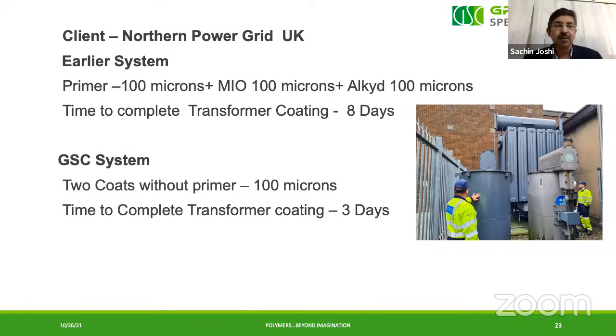And what are the systems? Earlier system: 100 microns primer, 100 microns MIO, and 100 microns alkyd. Time to complete transformer coating is 8 days. So 8 days your revenue is stopped. When you change to this, only 2 coats, 100 microns, and within 3 days we are handing over the transformer to the power grid. So you can see 5 days of revenue is saved, labor is saved, and there's a lot of cost saving with better performance.